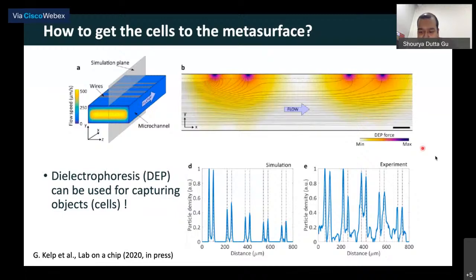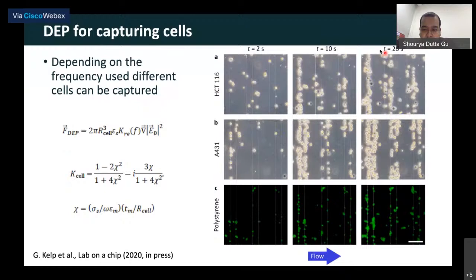So this is the experiment that we have done, right? Again, you see a very similar variation, with maximum density of particles at the edges where the electrodes are. This is a typical experimental image that we get. Here we have different kinds of particles. This is a fluorescent polystyrene particle, and these are two cases of different kinds of cells. Now, if you look at the dielectrophoretic force, which is given by this equation, you will have the gradient of the electric field, which is why the field is maximum and the force is maximum near the electrodes.